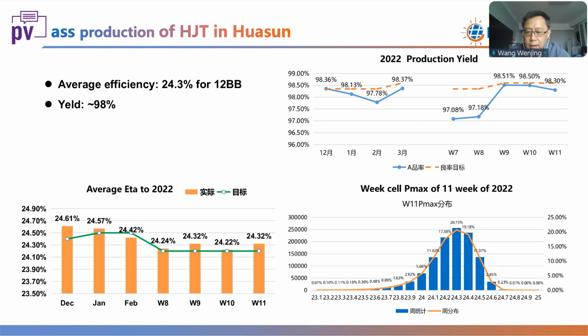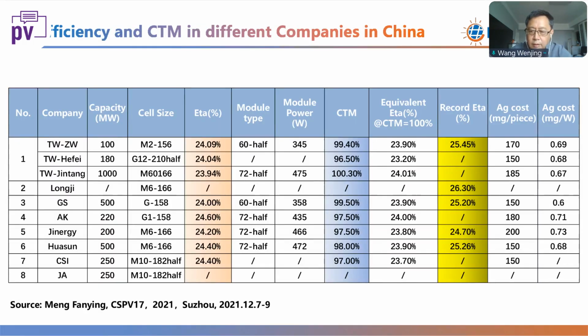Right now in Huasun, this kind of technology already goes into mass production. The average efficiency is about 24.3%, and yield is 98. There are also many other Chinese companies making this kind of heterojunction solar cell, but they report quite different efficiency. The CTM is also a little bit different. But if we take CTM equal to 100%, we calculate the equivalent efficiency from the module power. We find the equivalent efficiency is almost the same, around 23.9 to 24.1%.